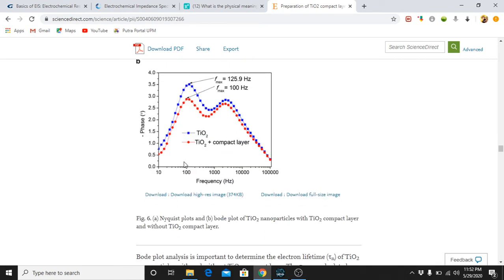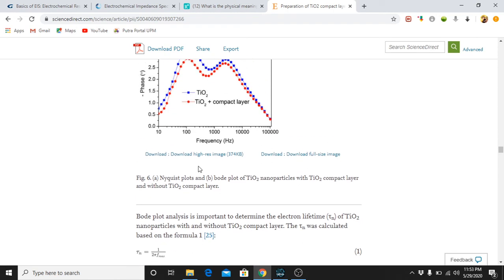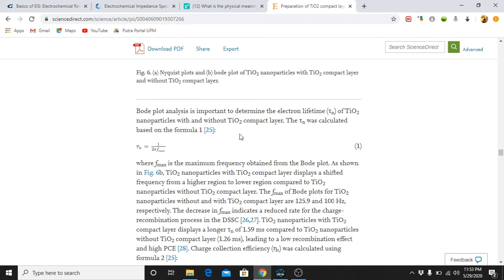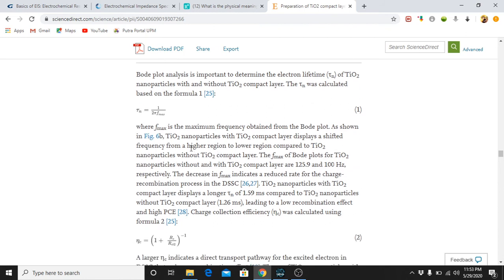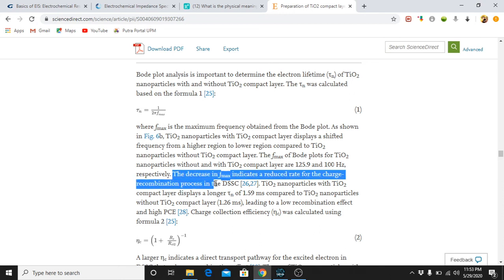Now, in impedance analysis we also have another plot, which is the Bode plot. What's important about the Bode plot is knowing the maximum frequency, so you can compare with and without the compact layer. As you can see, with the compact layer the maximum frequency is shifted to the left, so the Fmax value is reduced. A reduced Fmax is good because of the formula: electron lifetime tau_n equals 1 over 2 pi Fmax. A decrease in Fmax indicates a reduced rate of the charge recombination process in DSSC. So by having a reduced Fmax, the recombination of charge is also reduced.